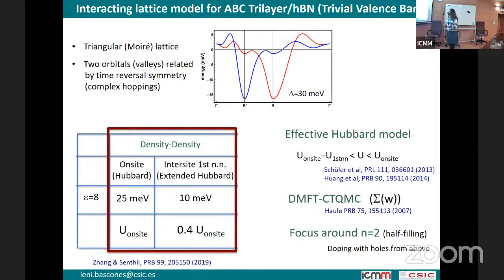So we can see that the two terms are sizable. So I'm going to simplify the model even more. To study the Mott physics, if this intersite interaction doesn't produce charge modulation, the main effect of the intersite interaction is to give a reduction, so it can be absorbed into a reduced Hubbard interaction. This is, of course, if we don't go to the limit of charge modulation. In fact, I'm going to focus on the case in which we have two holes in the system, at half-filling.